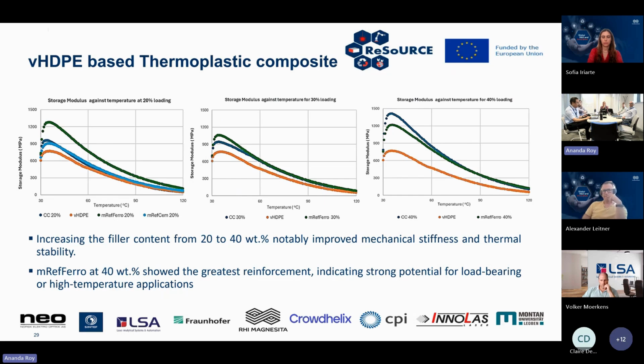But you can see that with the inclusion of these fillers within the system, especially with increasing filler loading, there is an increase in stability. And with up to 40% loading, the storage modulus is much higher, especially for the MREF ferro material system. Therefore, all of the systems evaluated state that MREF ferro provides a much more significant reinforcement within this polymer system of high-density polyethylene, making it a very strong candidate for applications requiring enhanced load-bearing capacity or performance under elevated temperatures.